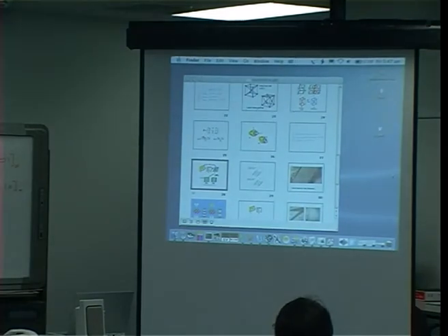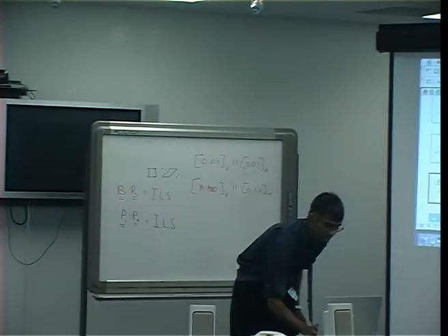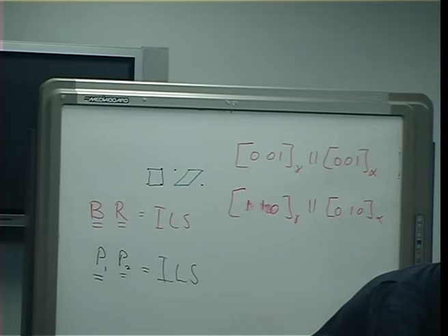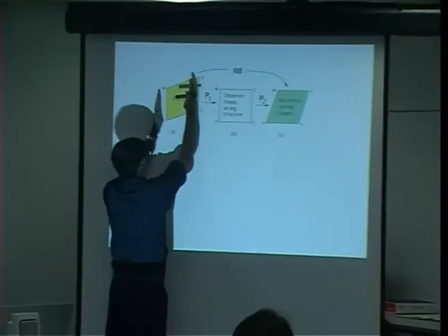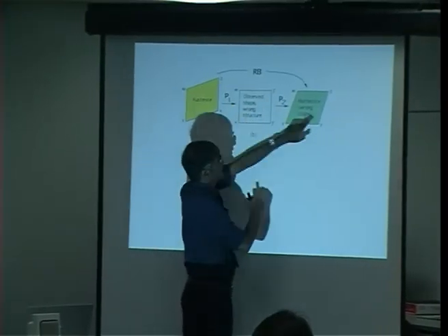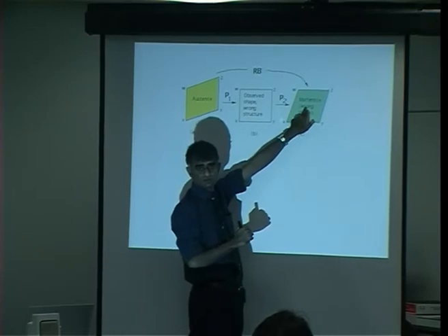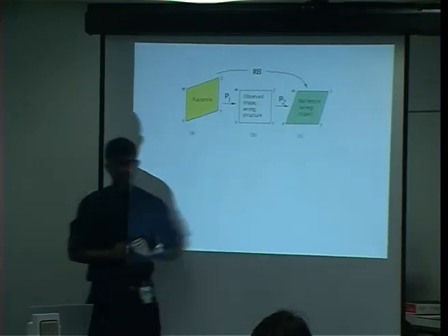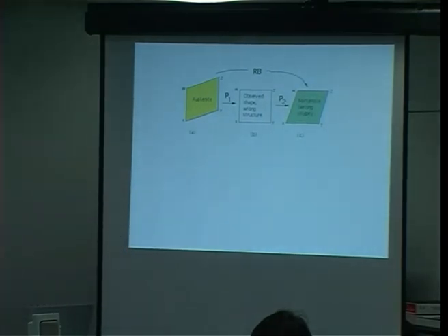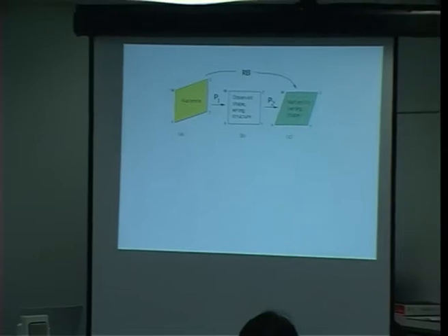When we combine two shears, we are left with a line which is completely unaffected. So P1 and P2 does in fact give us an invariant line strain. So the missing deformation is that if I add another shear on a different plane, and now another shear on this plane, then I get the correct crystal structure, which is martensite. But of course, I don't observe the macroscopic shape deformation which corresponds to two shears. I only observe one shear.